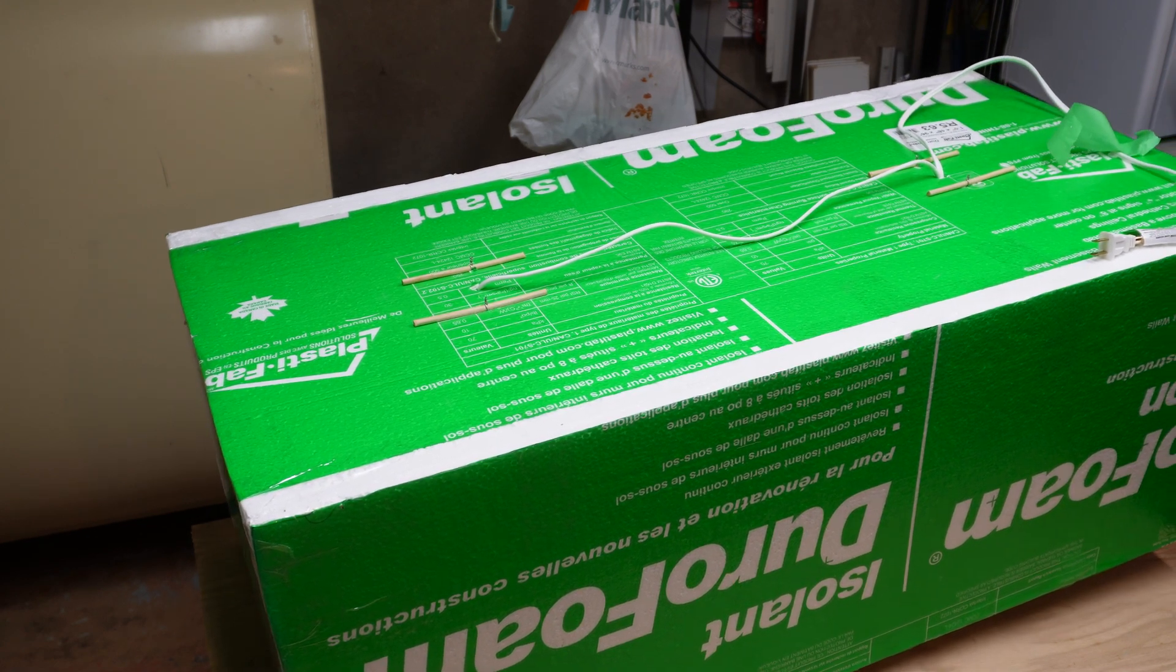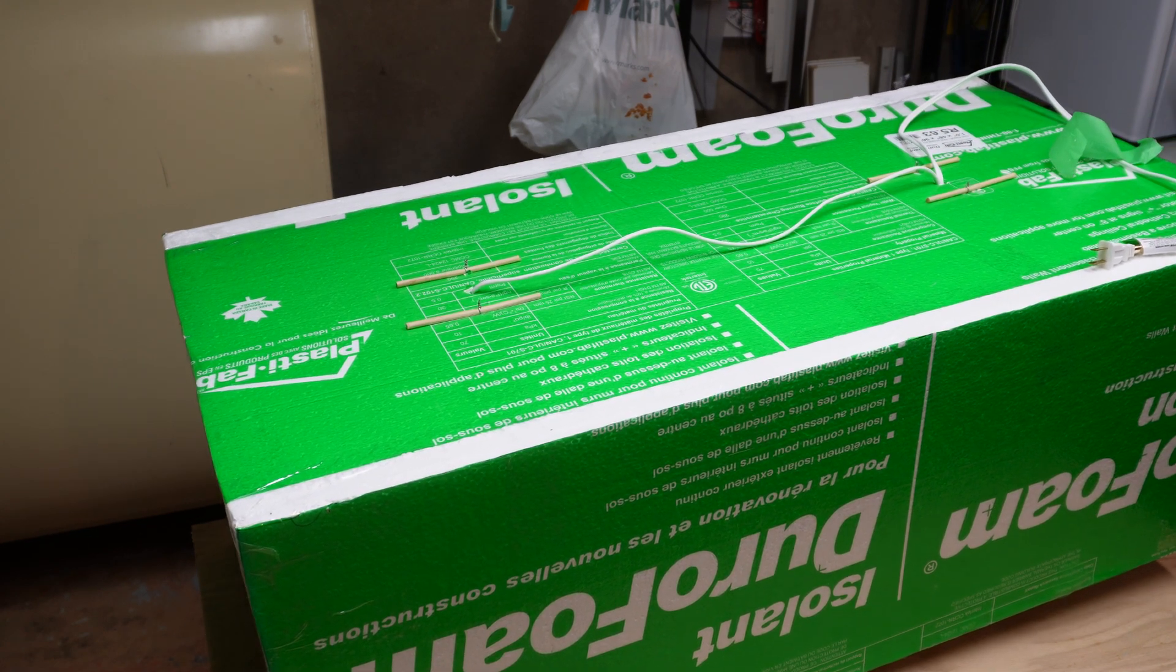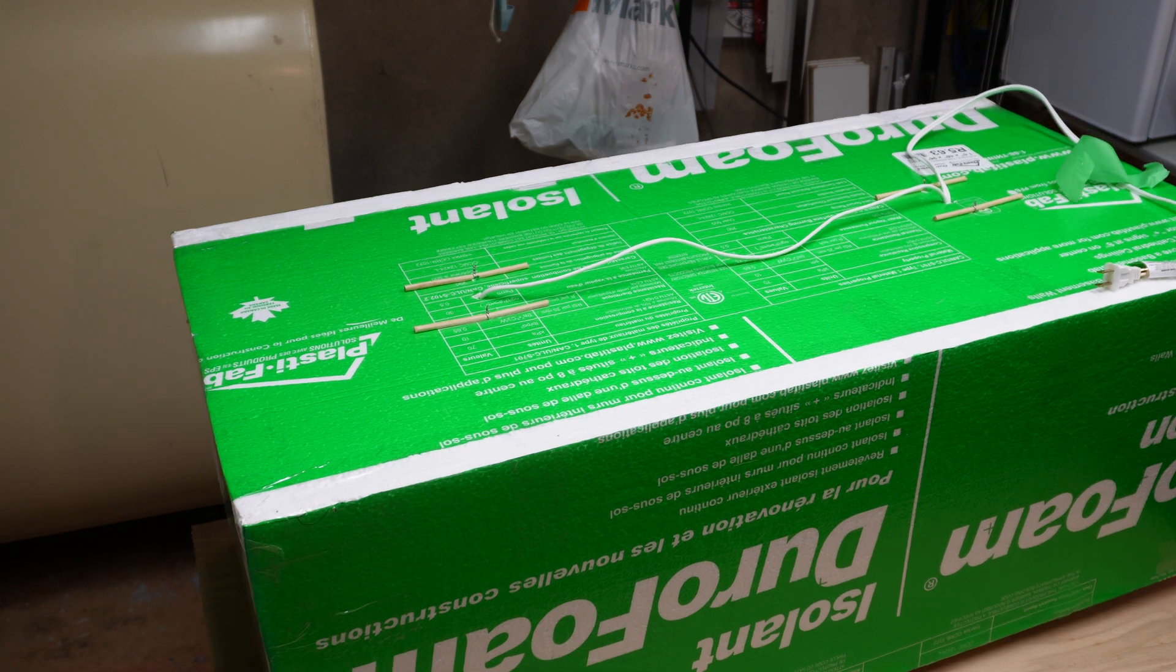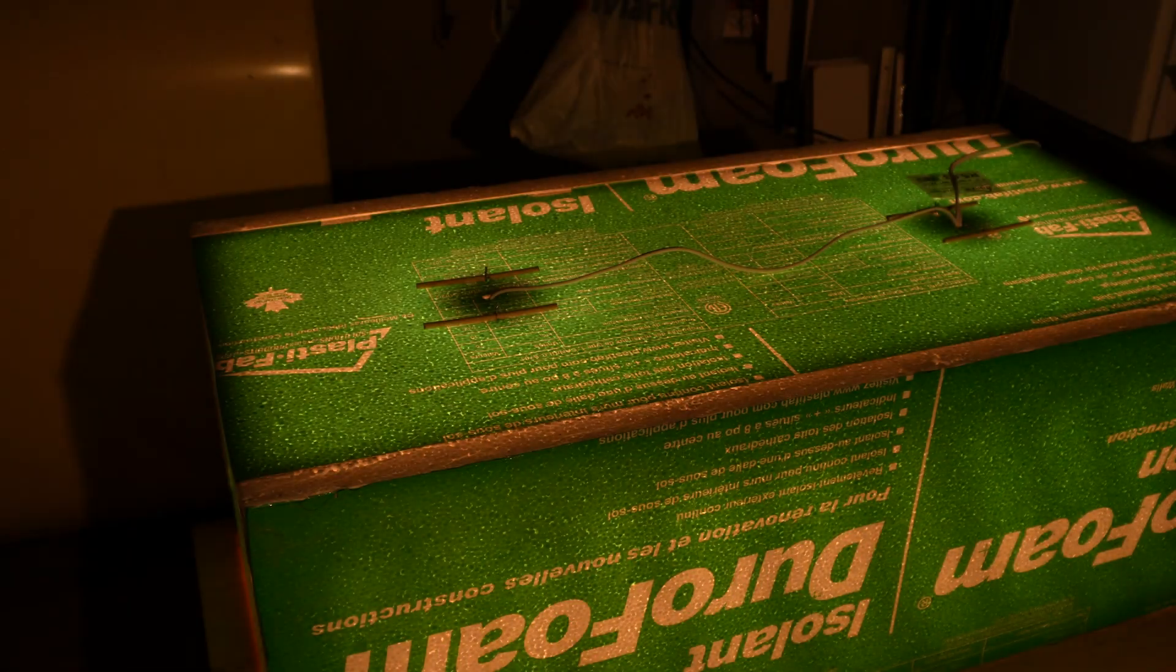Now all we have to do is put that hot box on top of our layup and connect the thermostat. I'll set it to 27 degrees Celsius and let that sit for 24 hours in this hot box before I touch it. I'd like to wish everybody happy holidays on this 2022 Christmas Eve. Don't forget to like, subscribe, comment. Peace.